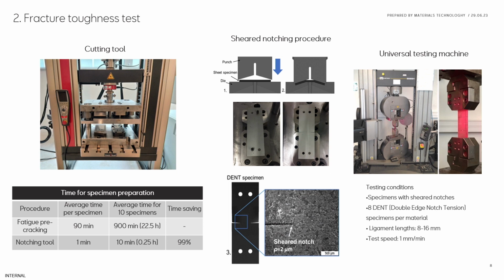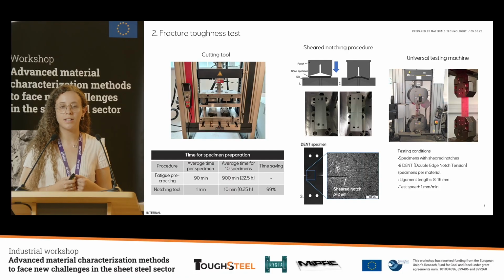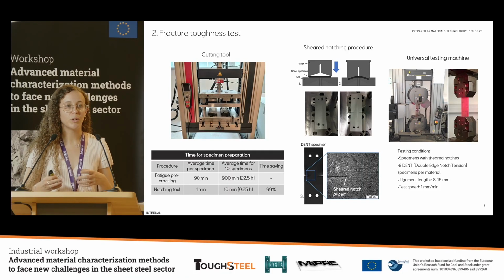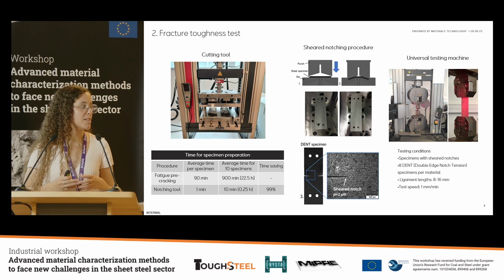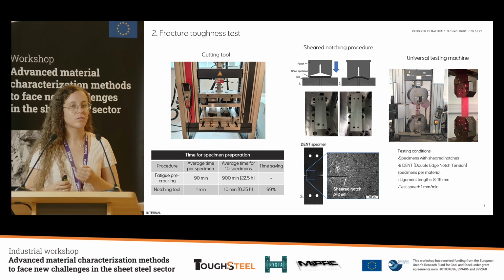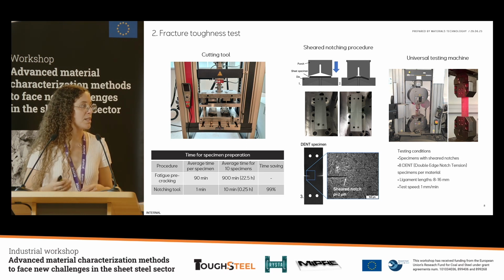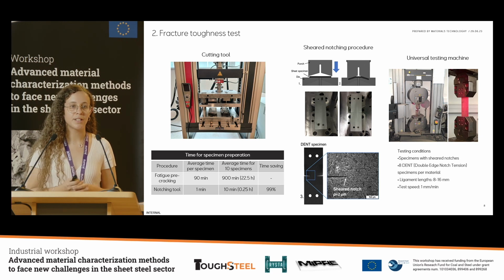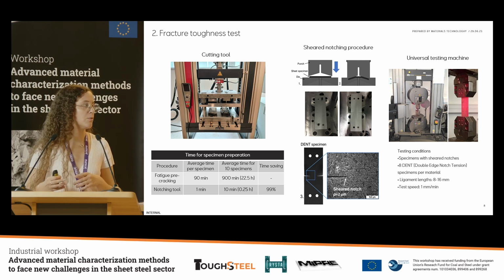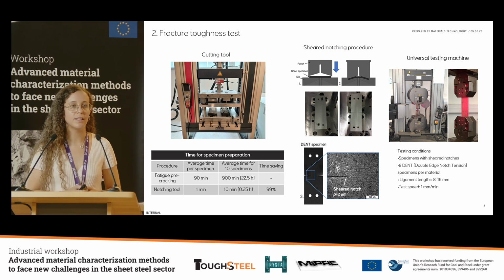Mainly, one of the important things is that we can set this tool to any universal testing machine, and we can create these two symmetrical sharp notches in just 1 minute. As we were saying before, to propagate a crack it takes 1 or 2 hours for one specimen if it works well. So we can decrease this time from 90 minutes to only 1 minute per specimen. To create a range of ligament lengths, which is what we need to calculate the essential work of fracture, we take only 10 minutes to create these cracks,